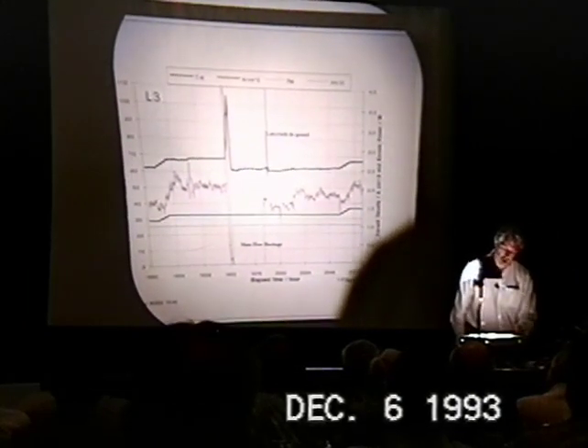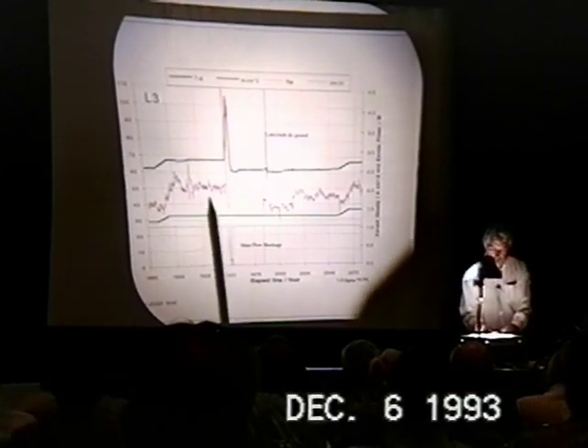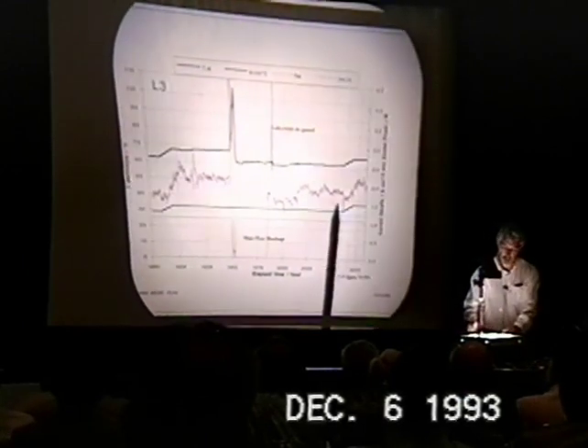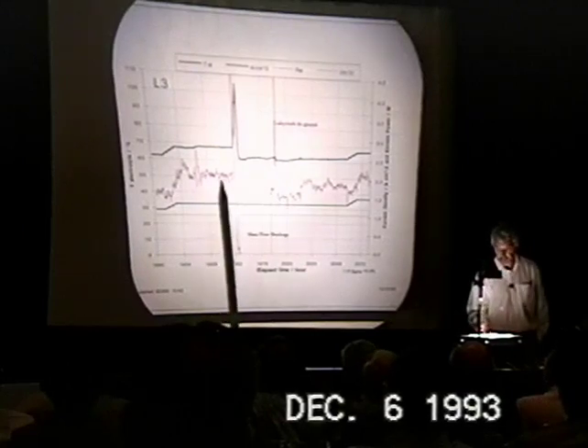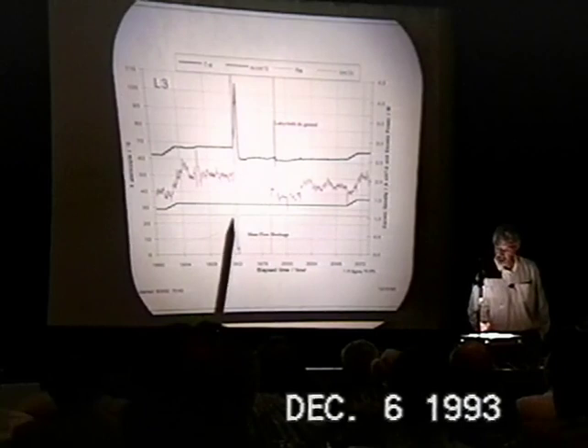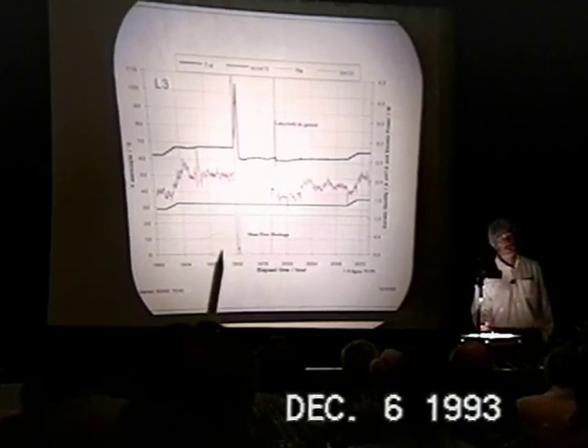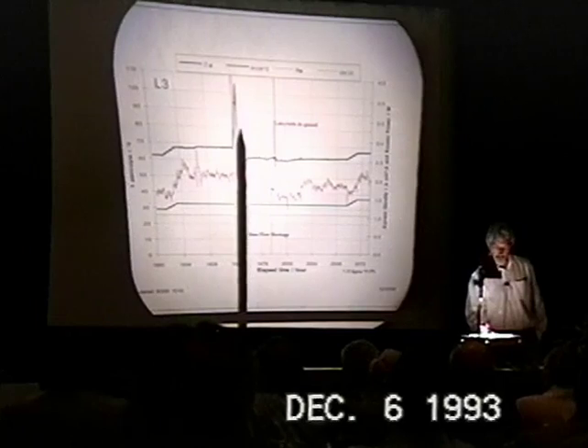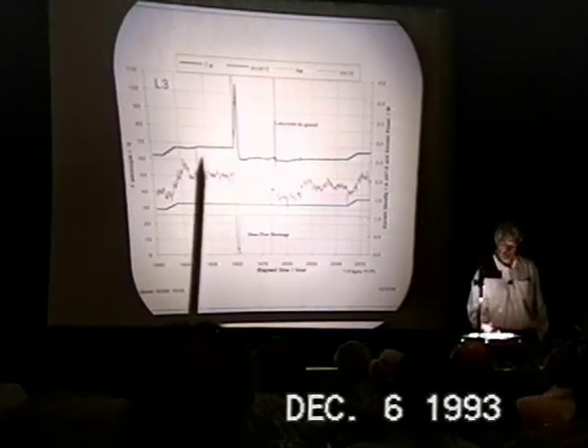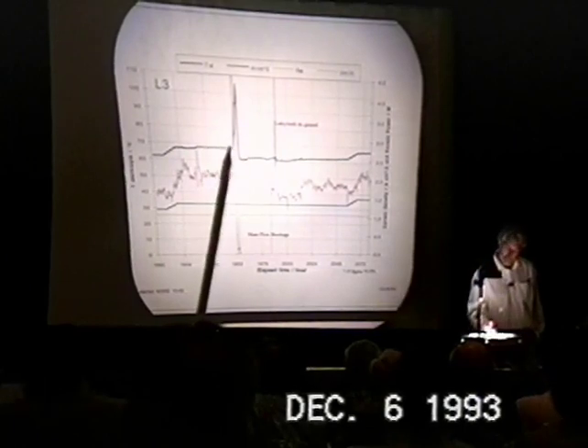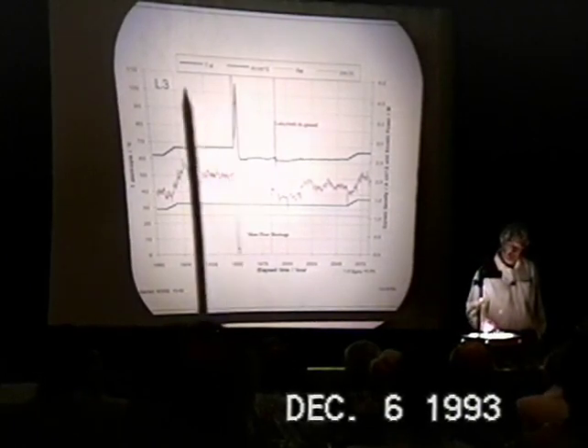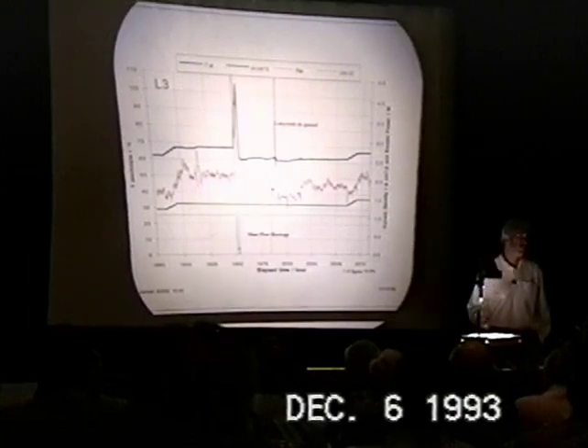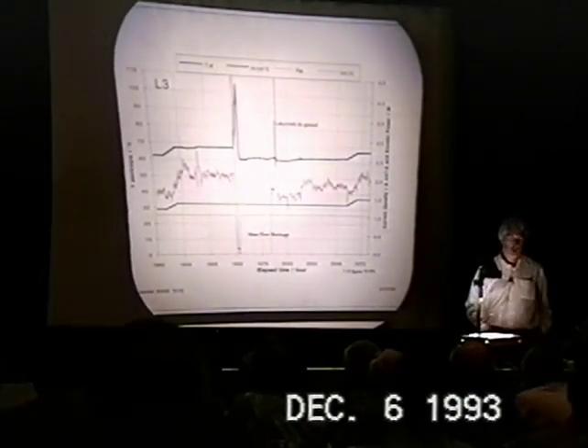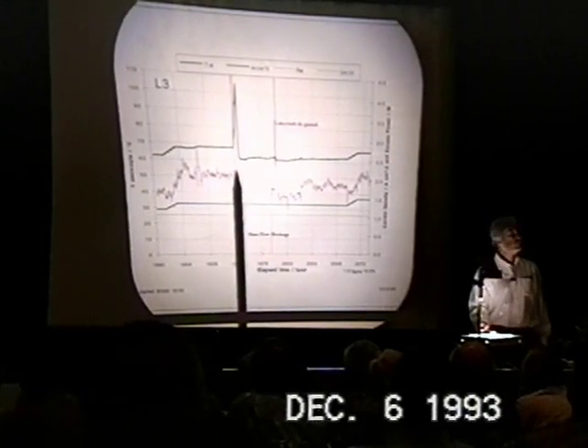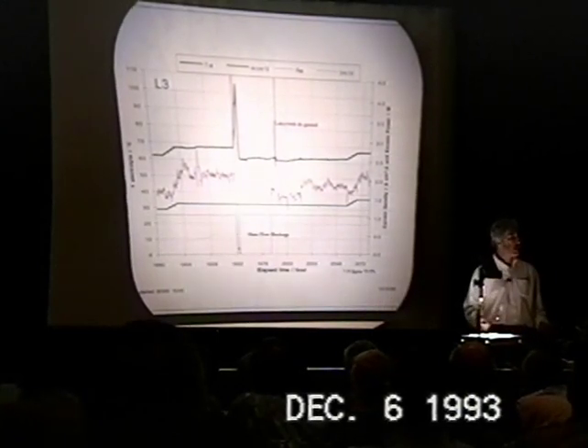This is the same region of time. Here is the calculated baseline excess power for this event. The mass flow blockage occurred at this time. Here I'm showing the mass flow rate in black, and the blue referred to the left scale. Electrolyte temperature increased, in fact, to a value of about 103 degrees at its largest value, as also did the excess power. So as the electrolyte temperature went up, the excess power went up fast.